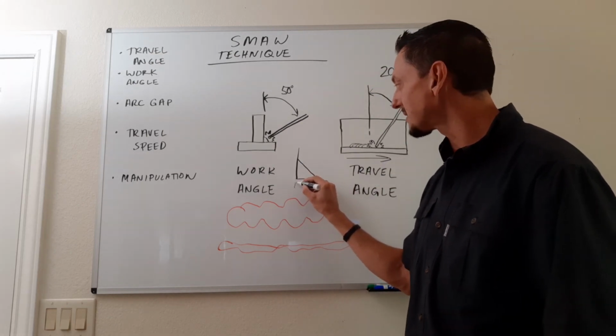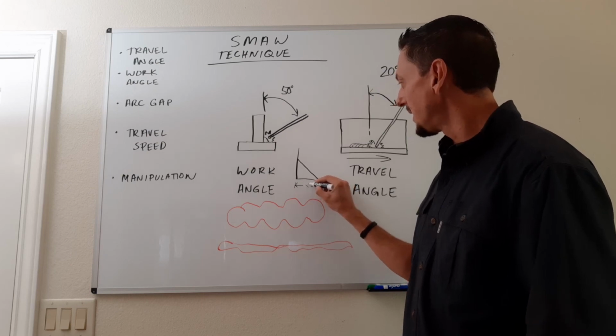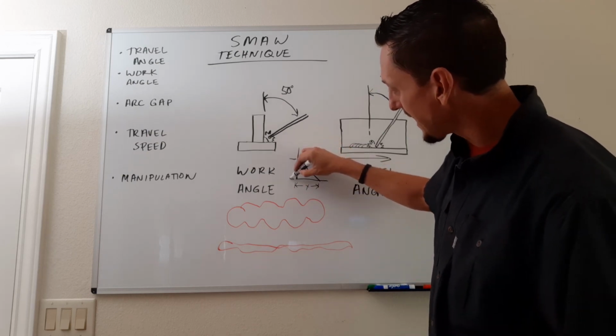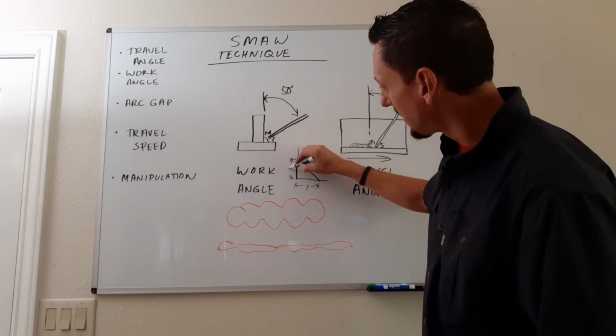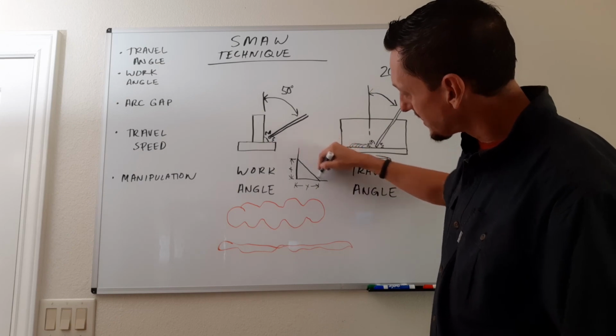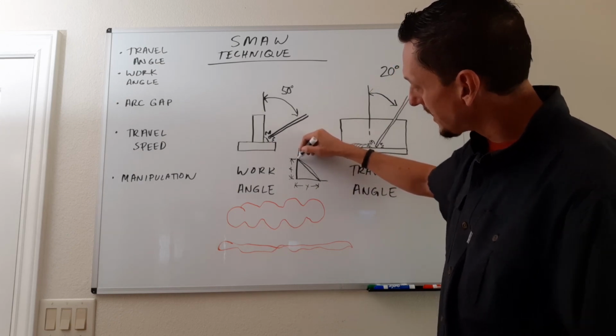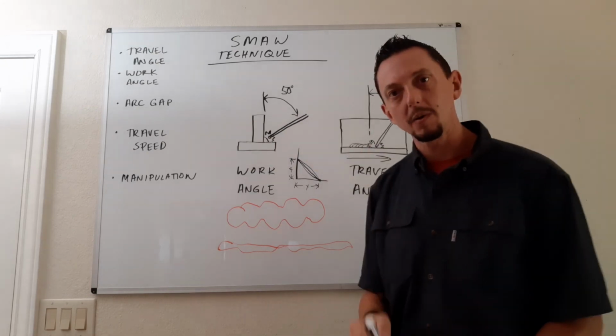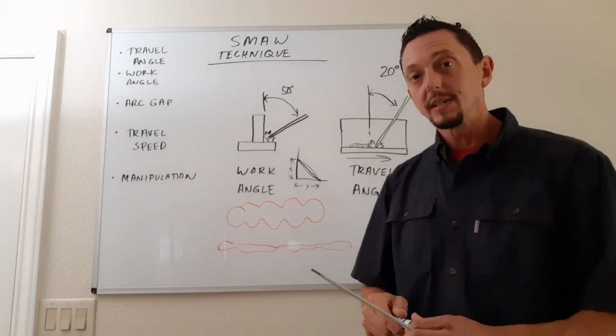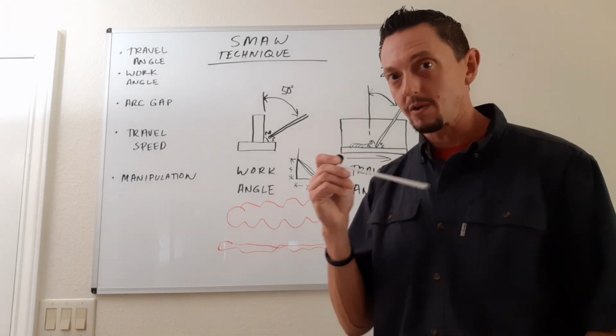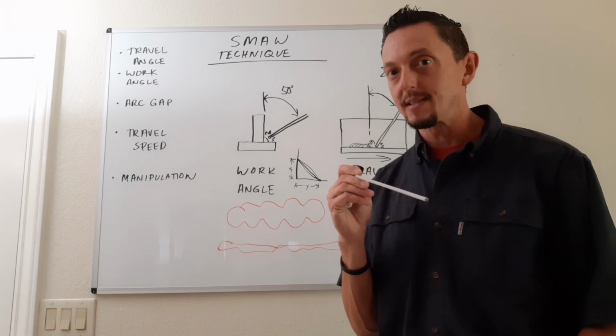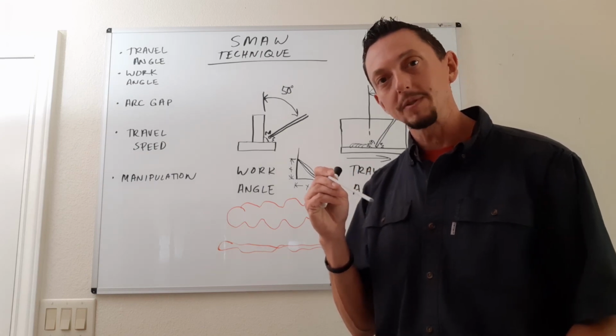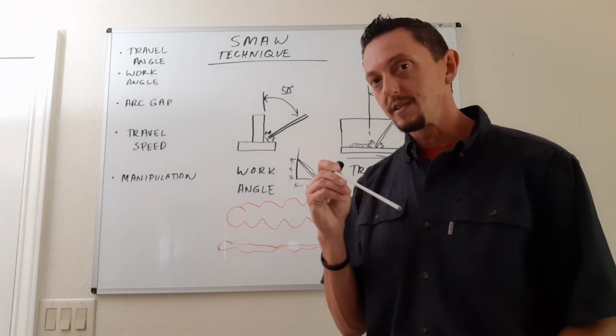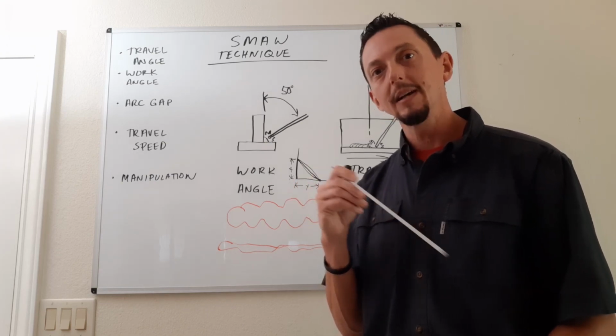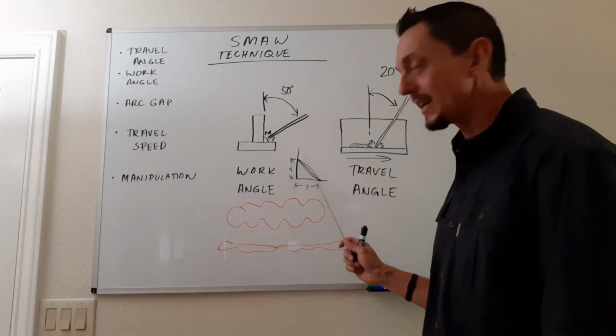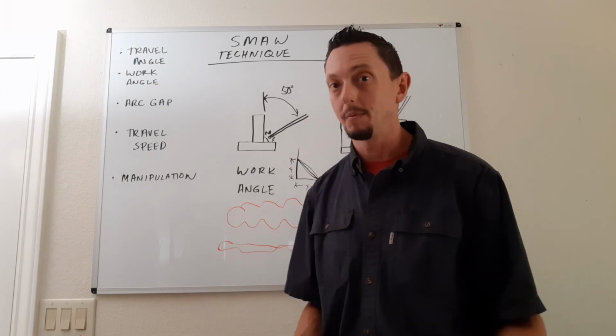We have equal leg lengths. So these lengths from here to here and here to here are the same. And we have somewhat of a flat profile. This is perfectly flat, a little bit rounded that way or just a little bit concave is okay. That's going to be an acceptable weld. So it doesn't really matter how we manipulate the electrode, if we're just going straight across, if we're kind of going like a pause and a stop, an advance and a stop, almost like a little bit of a whip, or if we're doing cursive E's or C's or a W pattern. It doesn't really matter as long as we end up with an acceptable profile. An acceptable weld is an acceptable weld in the industry.